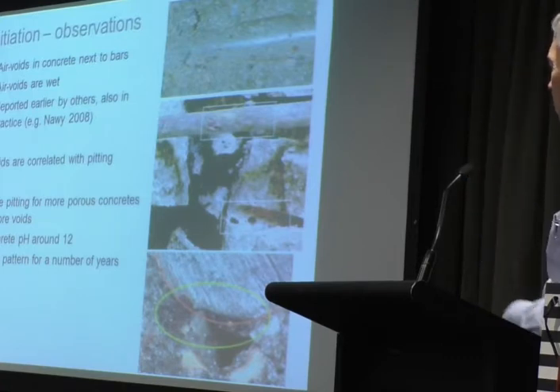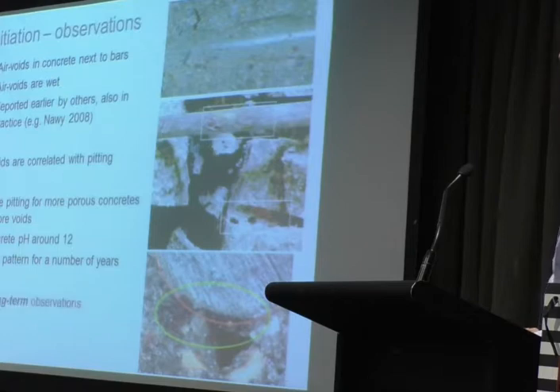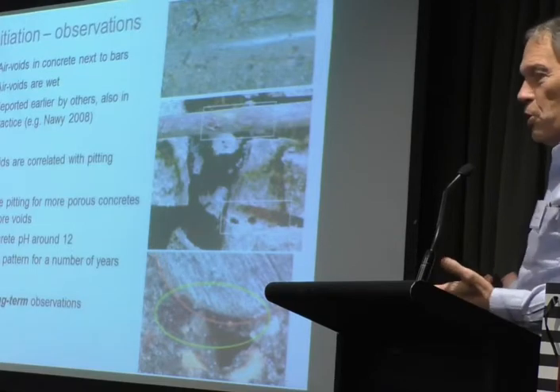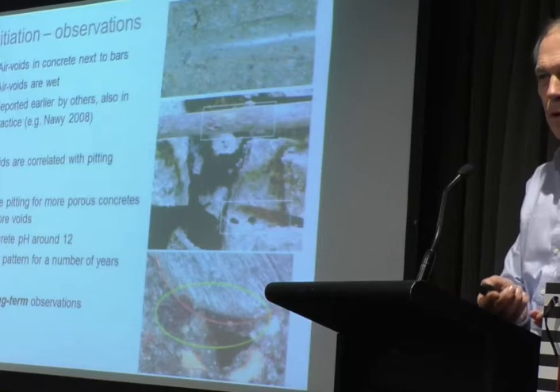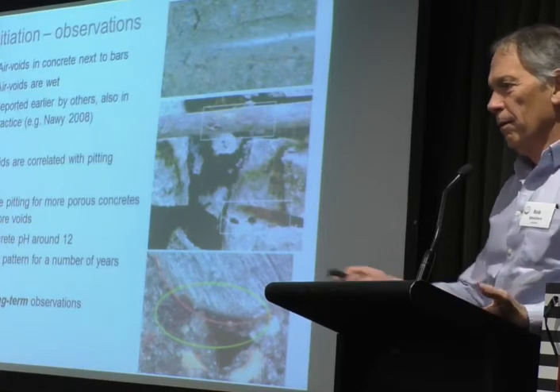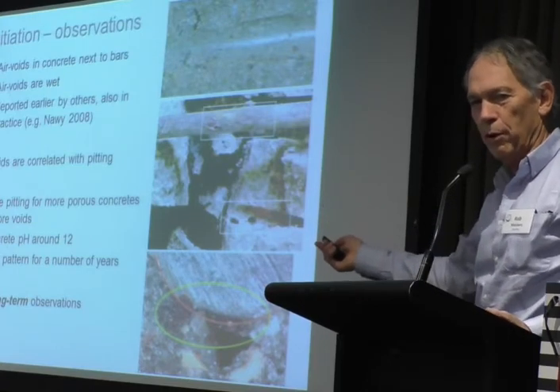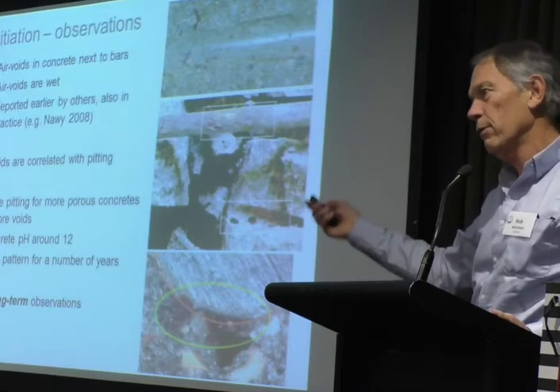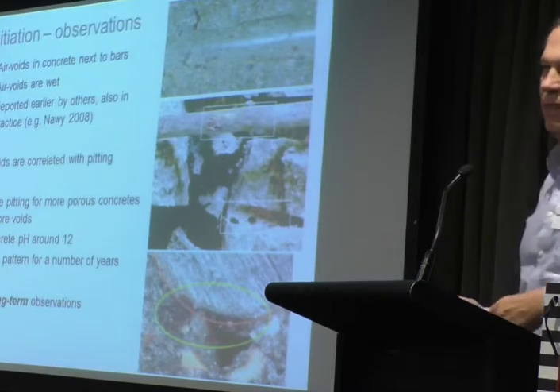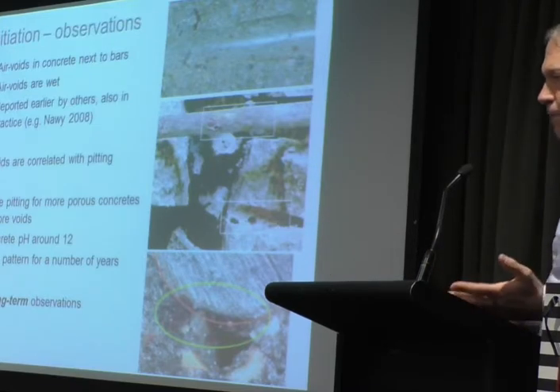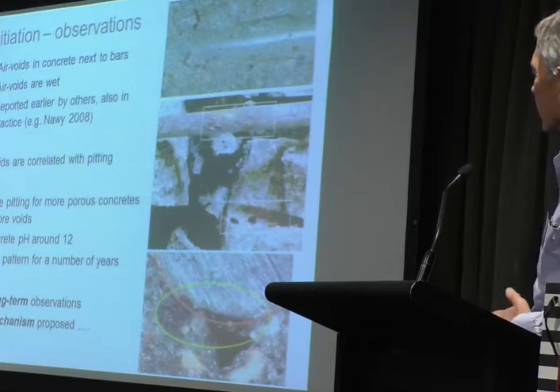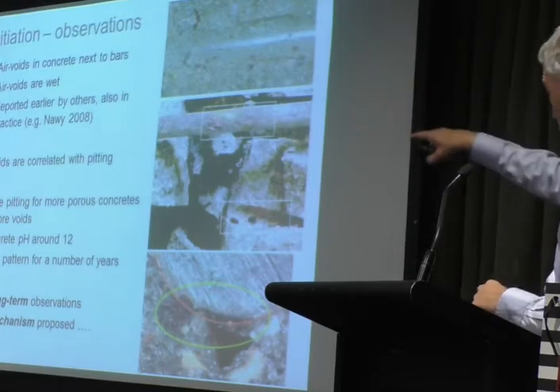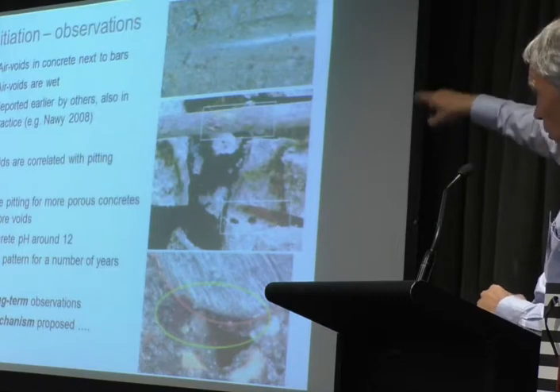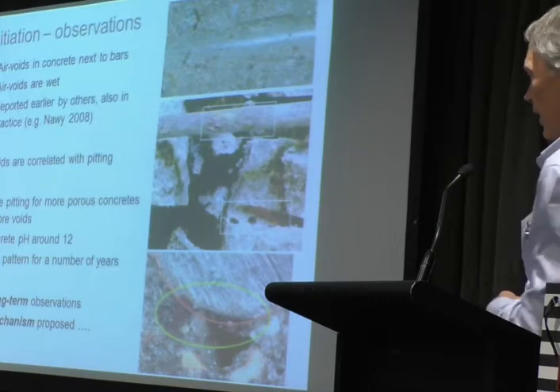And this is still with concrete around pH of 12, yeah. And nothing really changed. We saw that when we first broke them open after about 2 years to the most recent ones that we've broken open at 10 years, and now we're looking at year 13. We see exactly the same, nothing much changes. So what does that tell us? That in that curve, a bit of corrosion occurred and nothing much happened along for the next 10 years or so.